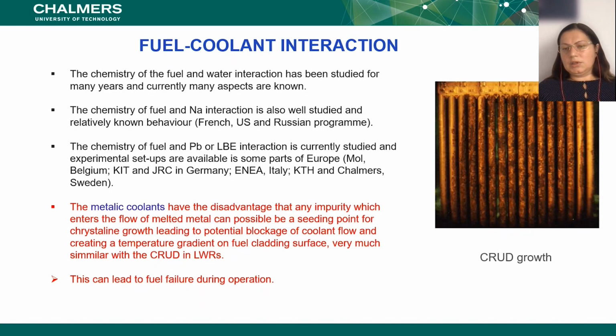So if you look at that, even in the current fleet of reactors, we have problems with things which are growing on the surface of the tubes. And here I'm talking about the crud growth. So crud is basically all kinds of aggregates which can exist from the water, impurities and so forth, and eventually they will come and react with the surface, which offers the best chemistry to get close to. And of course, this is a good chemistry. That means that you will get all kinds of compounds, and then you get this kind of growth, which has to be cleaned. Otherwise, the reactor will have problems, both with the water flows and also some points where the temperature is not the same as in the areas where it's clean.